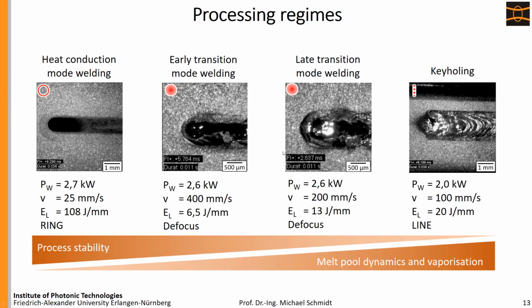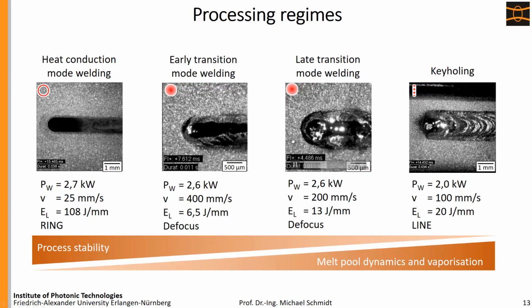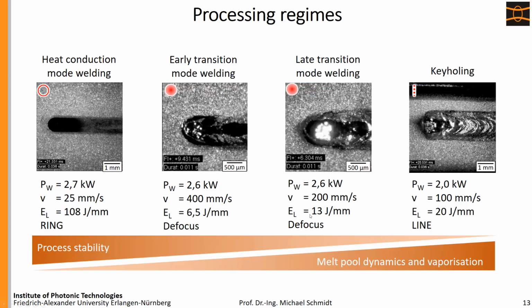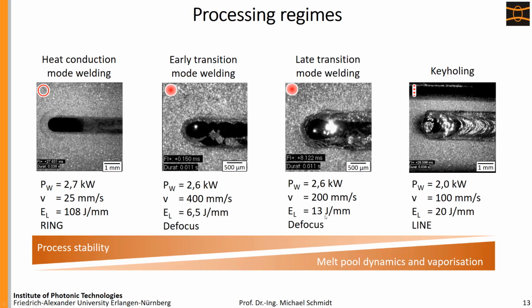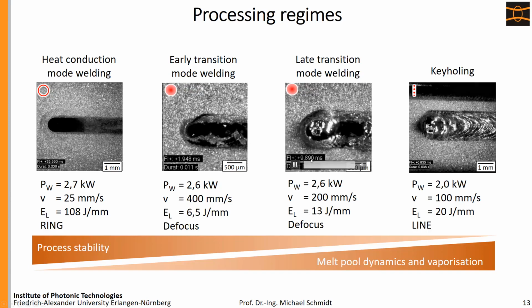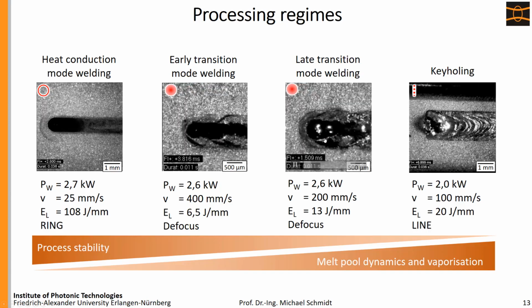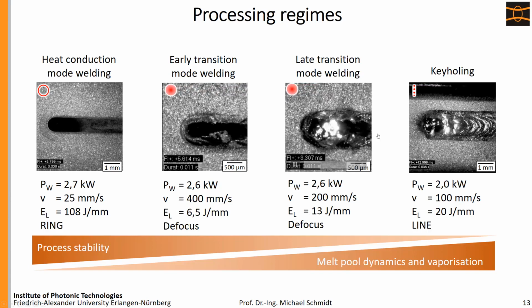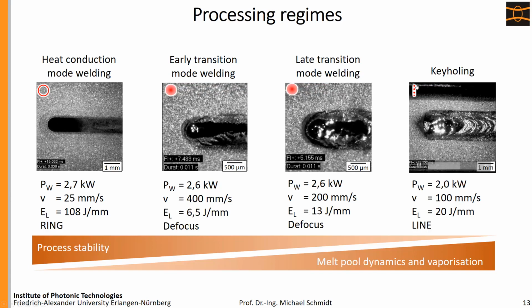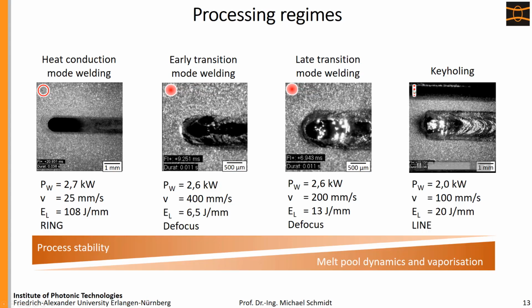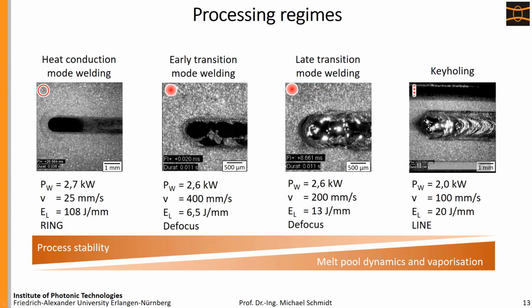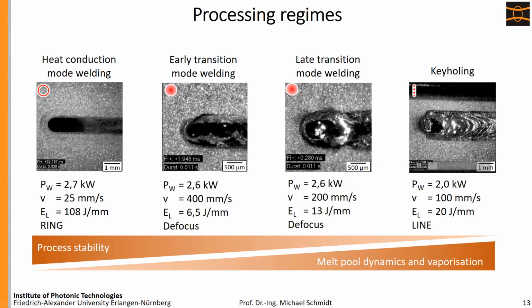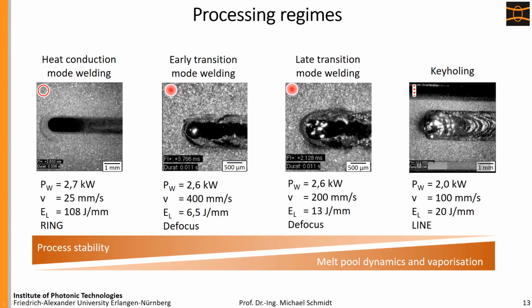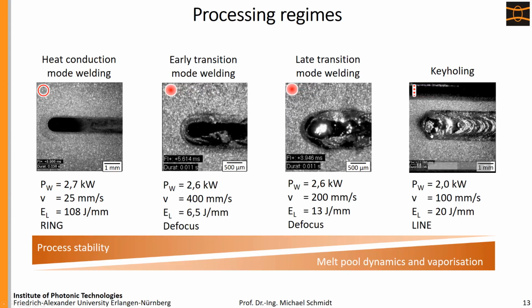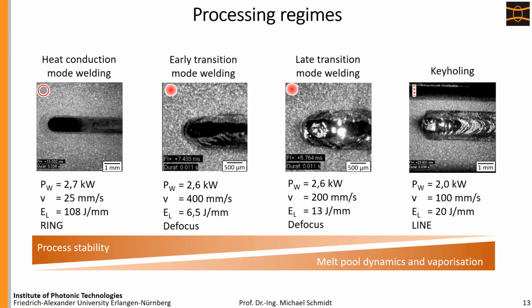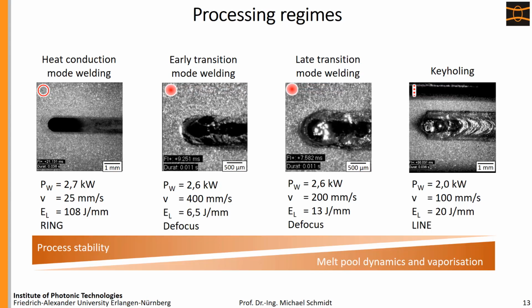So this is with a little bit higher line energy, as you can see here, from 6.5 joule per millimeter to 13 joule per millimeter, again with a defocus. And you see that the dynamics are getting higher, whereas here with a dotted line, so with the single dots, we already have keyholing, and you see spatters coming out of the material. Even though this is still not powder, this is still the metal material.